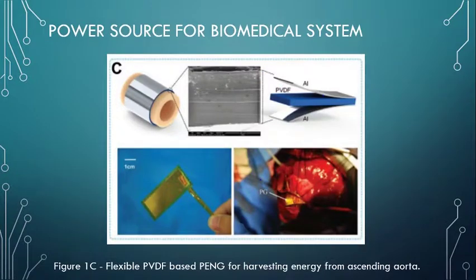Zhang and others report a PVDF-based flexible and implantable PENG, which wrapped around the ascending aorta and scavenged the energy from the pulsation. This research reveals the in vitro and in vivo studies of harvesting the energy in artery pressure with a flexible and implantable PENG. In the in vitro study, the max output power, voltage, and current of the PENG were 861 nanowatts, 10.3 volts, and 400 nanoamperes respectively. The quantity of electric charge per pulse was about 7 to 9 nanocoulombs.